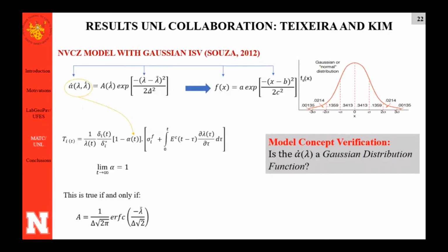So I tried to investigate other models available of damage propagation rate. And by looking at this model that is based on a Gaussian function, you can see the mathematical description of this model. It's similar to the mathematical description of a Gaussian function because it was made based on this assumption that the material follows a Gaussian function. So the shape of the model has the shape of a Gaussian distribution function. So I tried to use this model that uses this internal state variable.